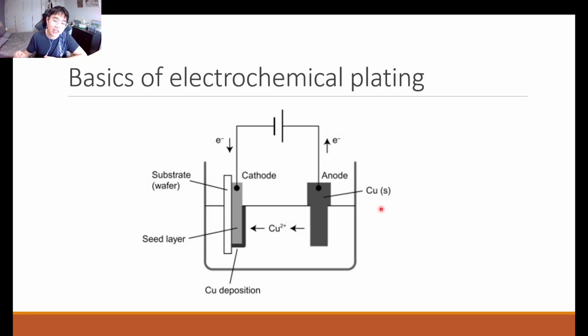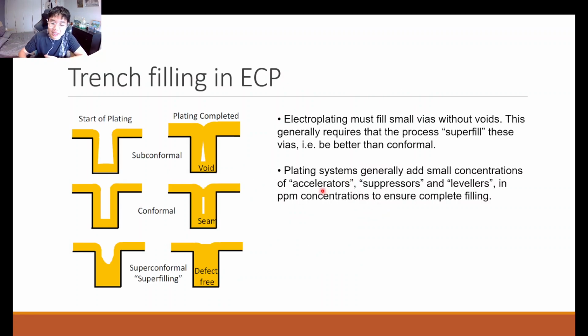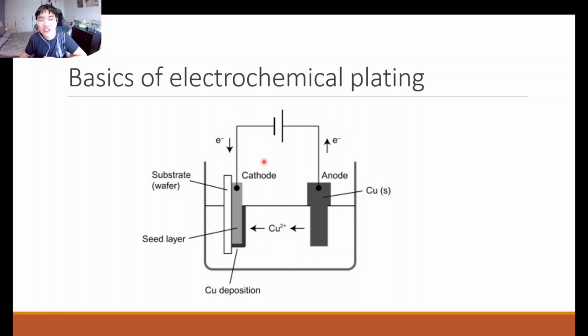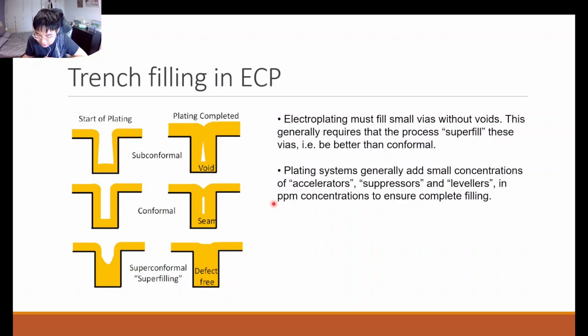So actually a lot can be discussed about electrochemical plating, but I will not discuss the very nitty-gritty details in this video. But compared to, let's say, plating jewelry, where we just want a uniform coating around the ring or whatever jewelry that you are plating, in the case of electrochemical plating for the interconnects in the semiconductor wafer, note that we are filling trenches and we are filling vias. So these trenches and vias can be very high aspect ratio features. This means that the electroplating step must be able to fill these high aspect ratio vias and trenches without leaving voids in between.